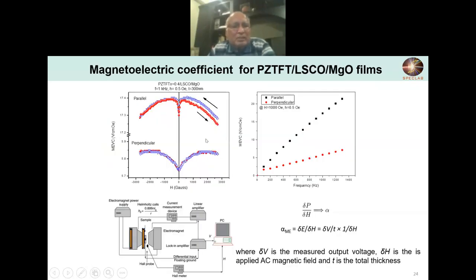Coming to the magnetoelectric coupling in this material, this is very surprising and very nice. This work was done by Professor Gopalan at Michigan, and we got coupling coefficients of something like 17.3 or 17.4 volt per centimeter. This is quite high. This was normally not expected in such materials, but we got indeed very good coupling. And so these materials are very promising. And as a function of frequency, it's even increasing further. So the PZTFT is a very promising material, and we are indeed interested in making various kinds of devices with this material now.